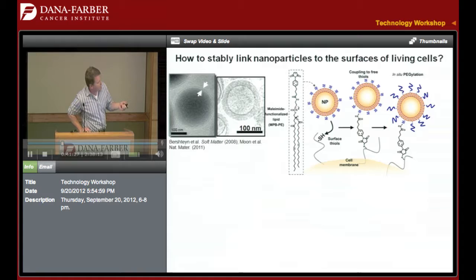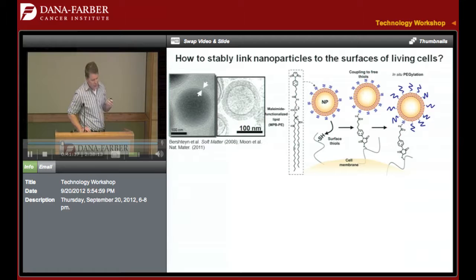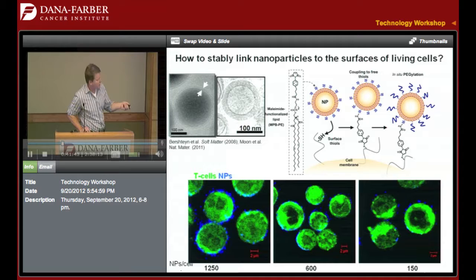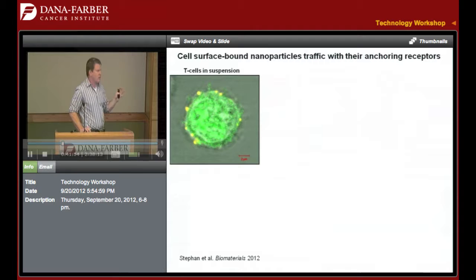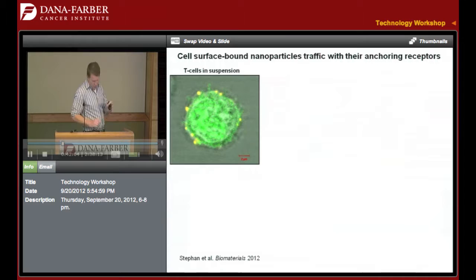For the chemistry, we exploit endogenous free thiols present on native cell surface proteins, using a thiol-reactive nanoparticle that links to the cell, then cap off remaining groups with polyethylene glycol. By mixing different ratios of particles and T cells, we can spontaneously decorate them with anywhere from a few dozen to hundreds of particles. Through a series of in vitro studies, we showed that with the right dosing — about 100 to 200 nanoparticles on a single T cell — we do not interfere with cell migration, proliferation, formation of an immunological synapse, or killing of targets.